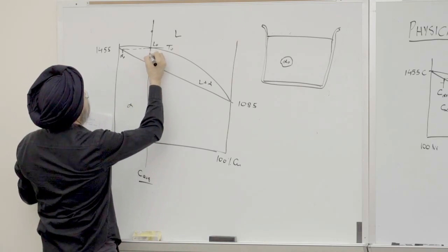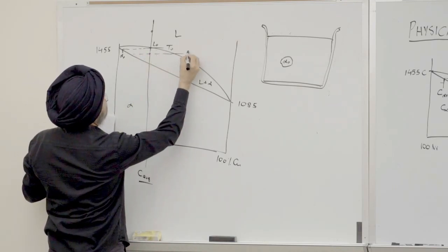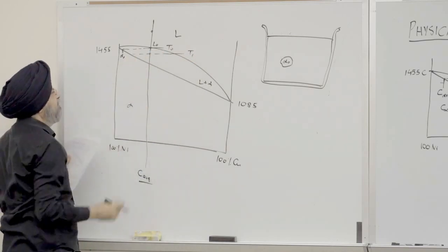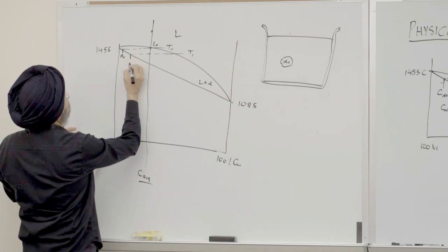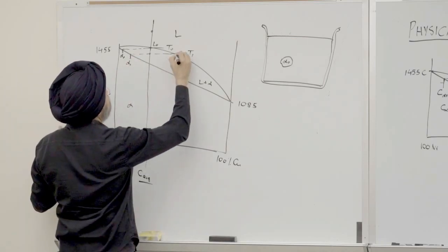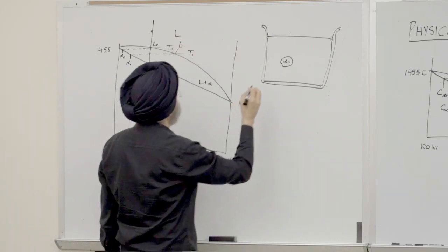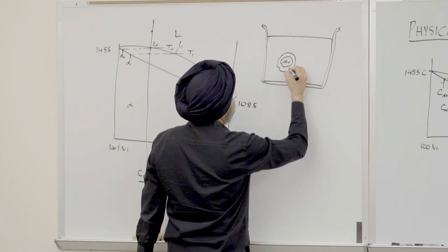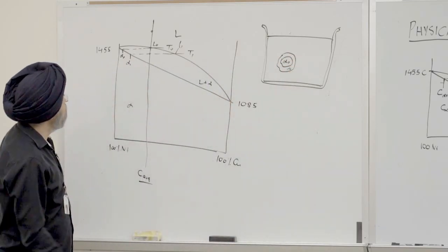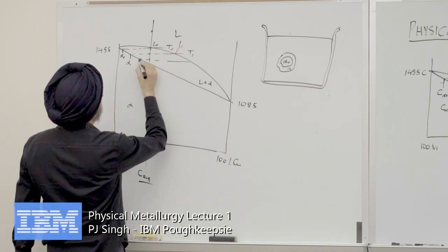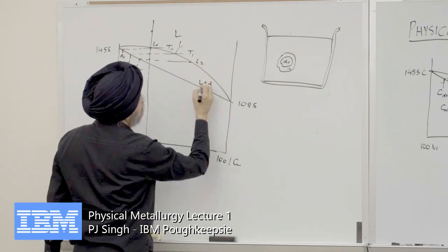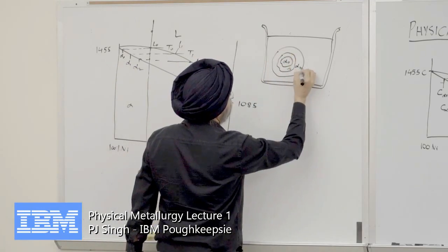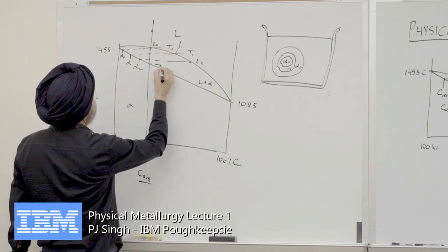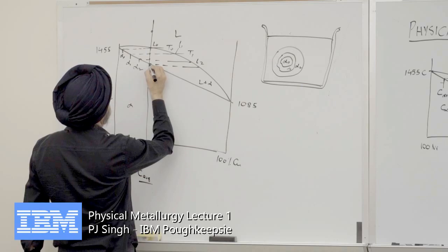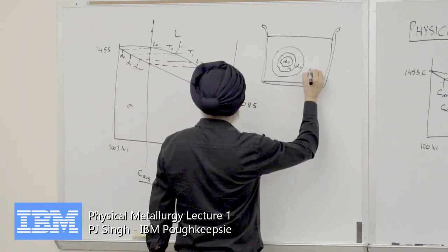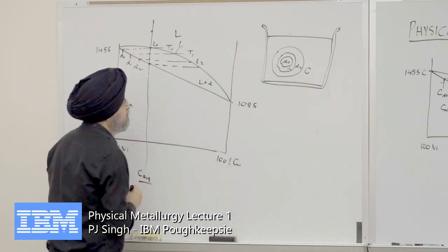So let me just jump to this temperature, I'll call it T1. So we went from here to there quickly, like instantaneously. So now the composition of the solid will be alpha 1 and the liquid will be L1. So this new material freezing out will have composition alpha 1, and then let me draw another one. So this is alpha 2 and this is L2. So this third one will be alpha 2, and then the last one is right here when we have complete solid, and that is composition C, which is this.